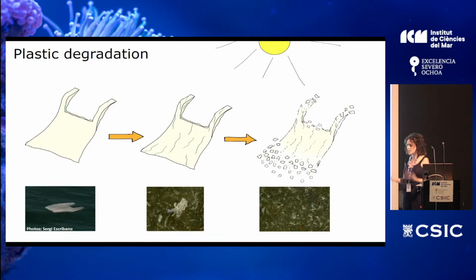When the plastic reaches the environment, it starts to degrade, and there are several factors contributing to the degradation. The most important is sunlight, but it can also be erosion, oxygen, high temperature. All these make the plastic degrade. And when we talk about degradation, it doesn't mean that the plastic disappears. It means that it starts to present scratches, brittleness, and it can break into fragments. When those fragments are smaller than 5 millimeters, they are called microplastics. But they don't disappear.